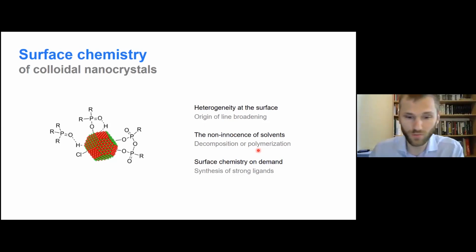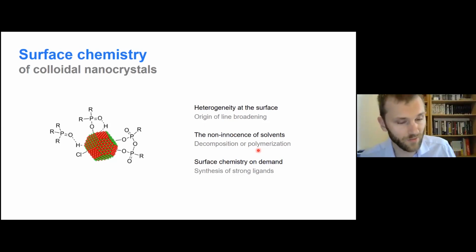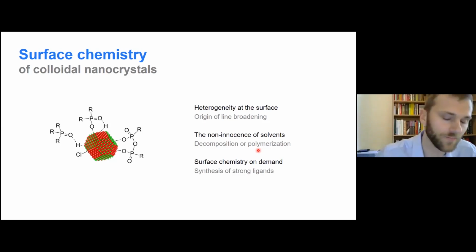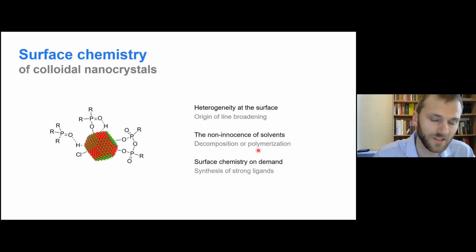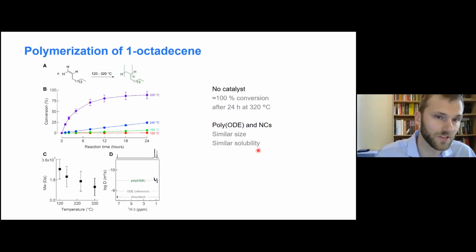And so if you move the beam, you see that you actually have made a big black circle where you were before. And people often describe this as organics. Oh, there are organics in your sample. And the question is, what is the name of this suspicious and elusive organics? And that name is polymerized octadecene, because that is a very popular solvent.